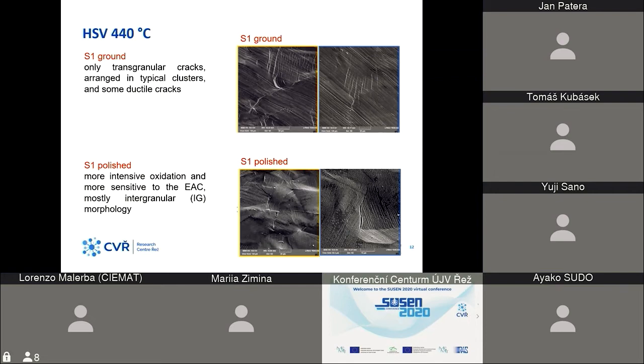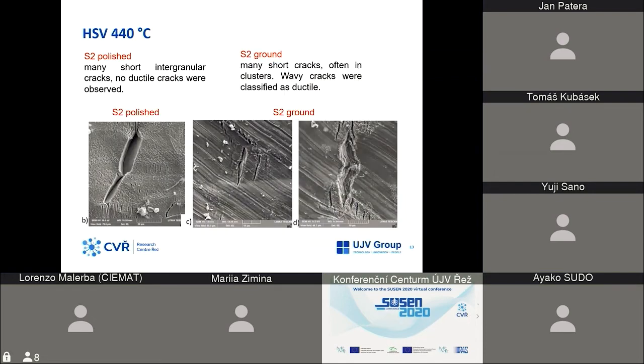When we were talking about the highest strain rate on the polished surface, we were observing many short intergranular cracks. They were more open in this narrow gauge region, and less open towards the wider end of the taper gauge length, and we didn't observe any ductile cracks. On the other hand, on the ground surface, many short cracks were observed, and they were also grouped in clusters. Those wavy cracks we found on the ground surface were classified as ductile after FIB investigation.